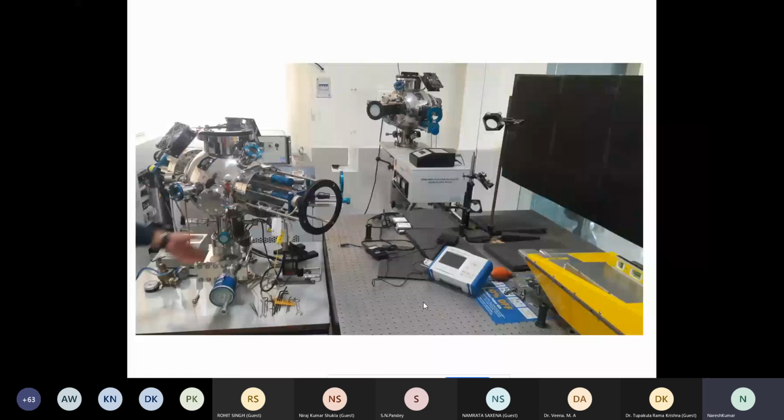But I tell you one thing which is very, very important here. These mirrors are not ordinary mirrors. One has to be very careful. These mirrors are not the ordinary glass mirrors, because here my wavelength is very particular and the energy of the beam is very, very high. So accordingly, we need to choose these mirrors. Mirror means a coating of material which will act as a mirror. So for a particular wavelength, I will be choosing a particular mirror, and that mirror is again expensive. So the setup is a bit expensive. If I'm using 355, I need to use mirrors accordingly. If I'm using 532 nanometer, then I need to choose these mirrors accordingly, right?